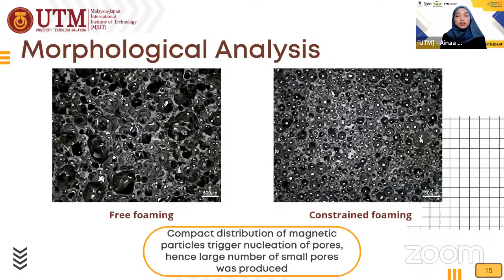This is mainly because of the restriction created during the constrained foaming, trapping more air required by the foaming process, and with the presence of magnetic particles, it will contribute more energy for the foaming took place. This will trigger the formation of pores, resulting to a larger number of smaller size of pores to be produced.